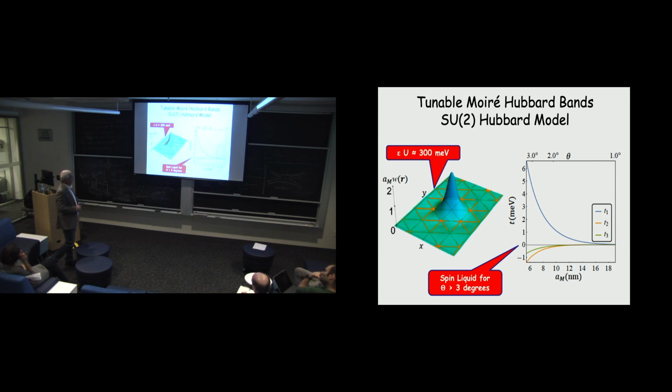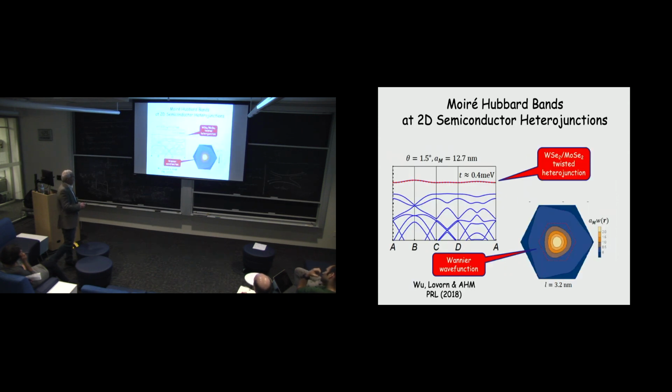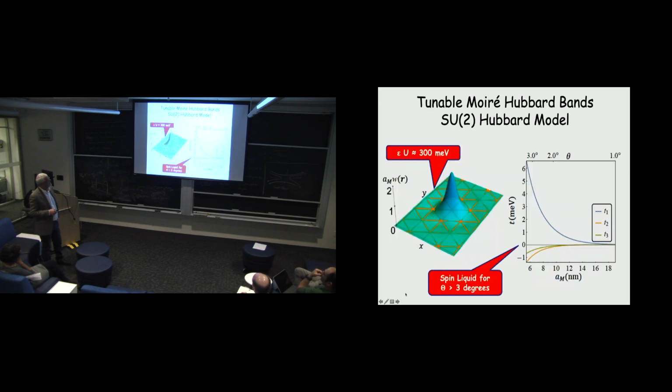It turns out that you can get to a region where one band of electrons, one energy versus momentum state, is well isolated from the others at twist angles of 1.5 degrees or so. And these bands, gaps between different bands, have been seen in experiment. So people are making progress on realizing this system.